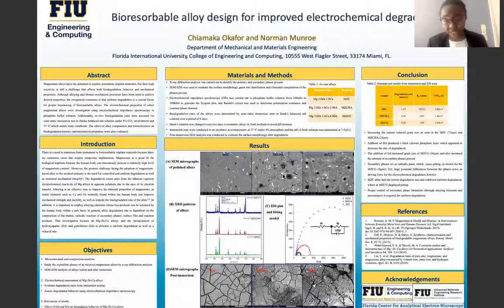We observed that as we increase the zinc percentage from here to here, with 1 zinc for MZC and 3 zinc for MZChE, there is an improved reduction in grain size. The addition of hydroxyapatite showed some kind of layer during the immersion test, which seemed to improve the decrease in degradation rates. The addition of gadolinium did not really keep the grain size reduced. There was a little bit of increase, and the amount of secondary phases present was more compared to the other two alloys, as shown in this image.